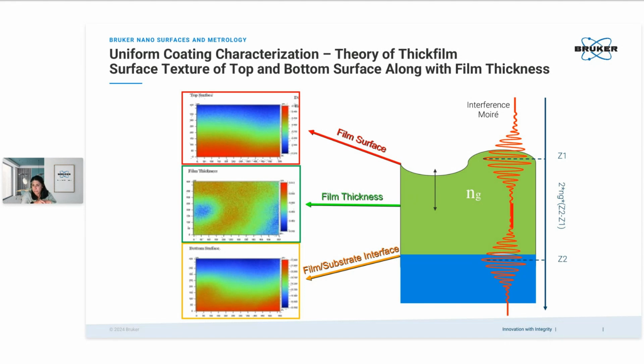The minimum reachable film is between 50 to 100 nanometers, which is more or less limited by most of the film materials, because below that height, the films are not opaque anymore. So on each coating interface, as you can see here, on the top of the film, as well as the interface of the film and the substrate, you can get the information, the fringes, and from that you can derive the thickness of the film.